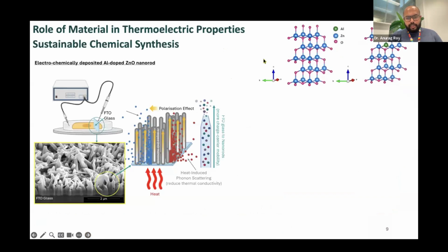So basically what we have done in this paper, we have electrochemically deposited the aluminium-doped zinc oxide nanorods. Look at the nanorods, they are very important. You can see here the nanorods, this is the SEM picture. The nanorods are doped with aluminium. The reason for doping with aluminium is to reduce the band gap, and at the same time, aluminium gives a polarization effect, so that you can get NIR absorption. Not a broad absorption, but a tendency of absorption if you dope aluminium in zinc oxide.